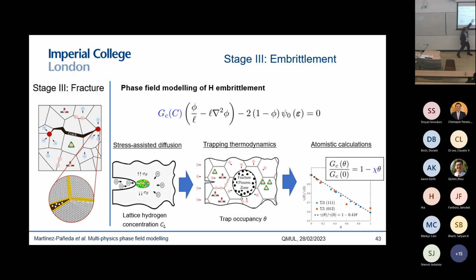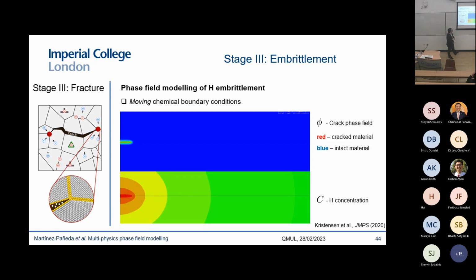We can then apply those trapping thermodynamics to determine what is the occupancy in that interface that we're interested in, like a grain boundary. And then we can go to these atomistic calculations and quantitatively predict what is the degradation in fracture energy. And we can do that. This atomistic calculation you only need to run once in your lifetime offline, and that's all. So let me show you some representative results with this framework.